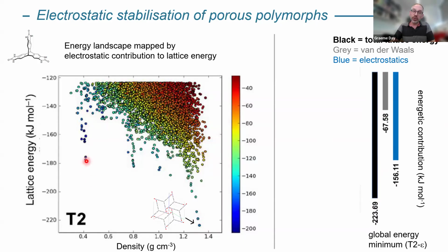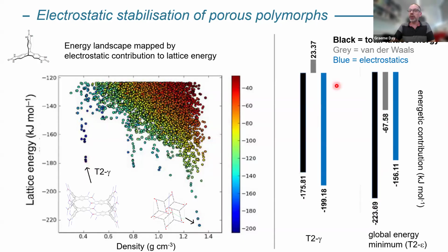Whereas if we compare to this T2 gamma structure here, in that case, because hydrogen bonds have lined up actually in a nicer way than in the global minimum, the electrostatics comes down quite a bit. So you get a good extra stabilization from electrostatics, but it's at the expense of these van der Waals interactions, which are now actually destabilizing the structure. So what we learned from looking at these breakdowns of energies are, what do we need to improve?